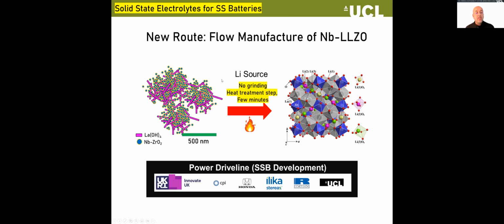So we've added our lithium source via incipient wetness. And what we were able to do, and the target, and this was on a big Innovate project with Honda and Ilika, who are one of the leaders in solid state batteries, what we were able to do was to make phase pure lithium lanthanum zirconate.